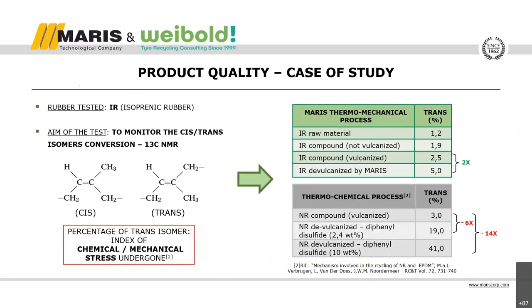From this slide to the next three ones, I'll show you four different kinds of analysis performed on our devulcanized product. In this case, the aim of the test is to evaluate the percentage of cis-trans isomers through carbon-13 NMR. The ratio between these isomers is strictly linked to the degradation in terms of chemical and mechanical stress. The tables on the right compare our results in green to some data from the literature about a thermochemical process.